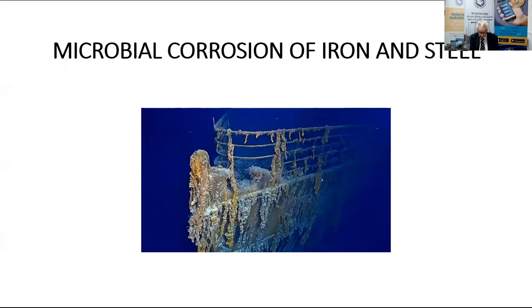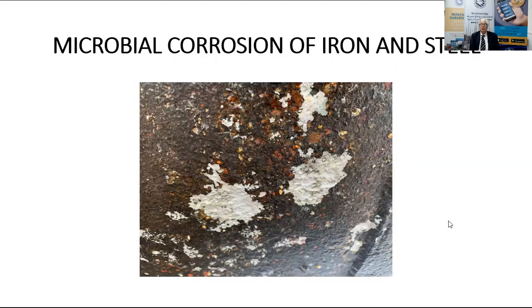It affects the precipitation of ferric iron solids. The flat bottoms of the pits, which are usually about 1 millimeter deep, formed by their action are covered with this silvery white tetrahydrated ferrous sulfate, also known in its mineral form as rozenite, and a clear identifier for the Thiobacillus group. Note also in the photographs below the high surface area to depth ratio of the pitting. You see the white silvery surface. That is typical bug attack, Thiobacillus ferrooxidans. When you see that, you know exactly what is happening to the steel. I'll tell you how to deal with it in a minute.